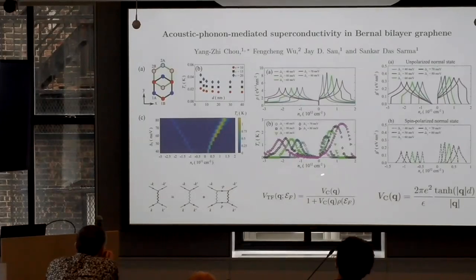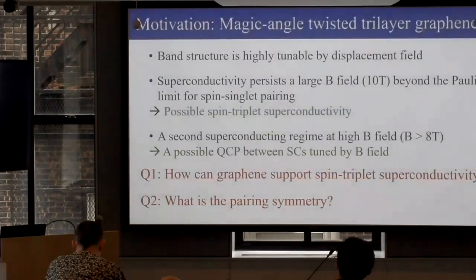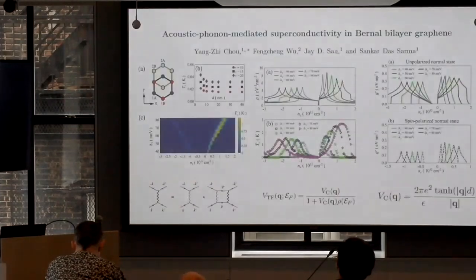So I said we have to include screening by the carriers themselves. And that we know how to do within the ladder approximation. So we did that. We included that. And amazingly, TC did go down to almost the experimental values. After including the mu star effect, we get results which are not quite, but close to it. So this is what the story is now.